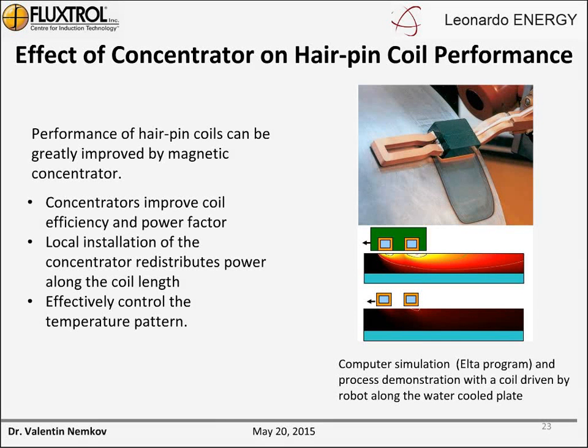The hairpin coil has two areas. One is without concentrator, left side, and then the right side has the soft magnetic composite concentrator. And you can see that the heating intensity is completely different. And computer simulation made with ELTA program confirmed exactly this result. Actually, this experiment was designed using preliminary computer simulation.